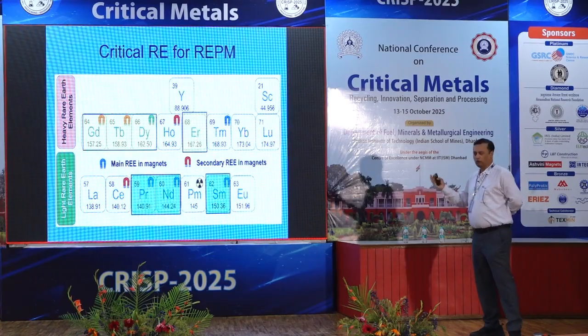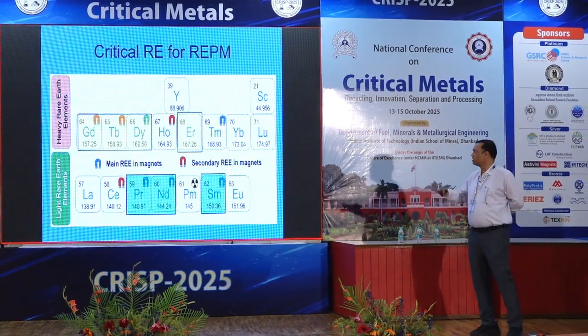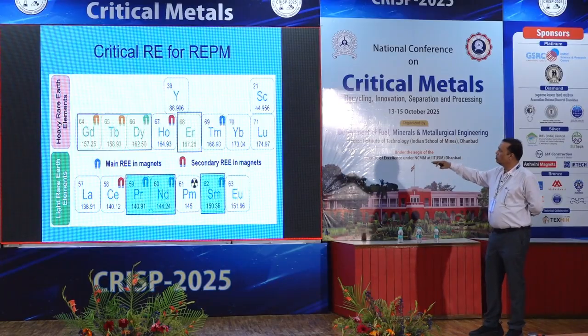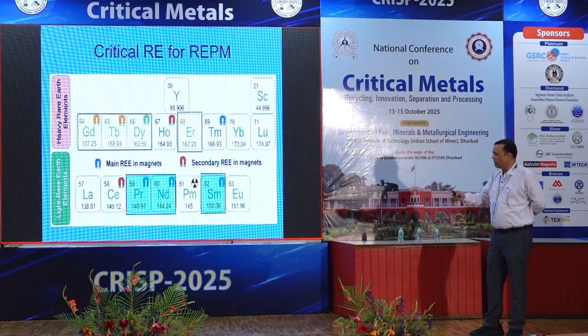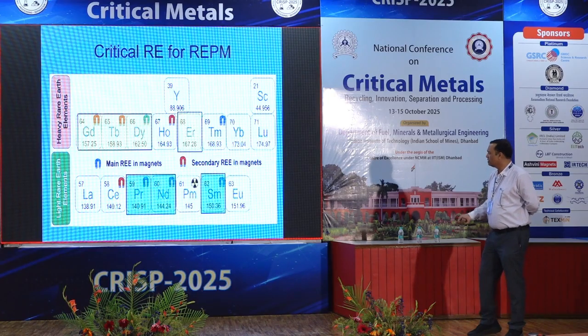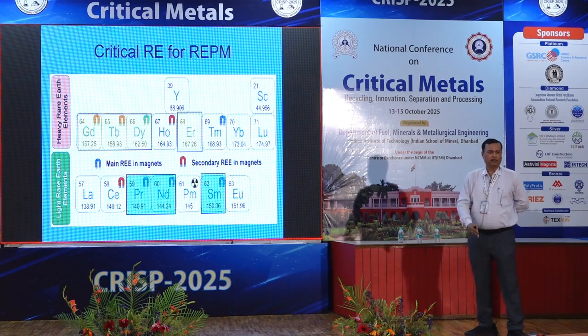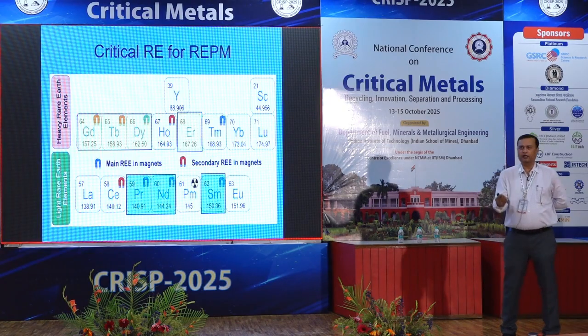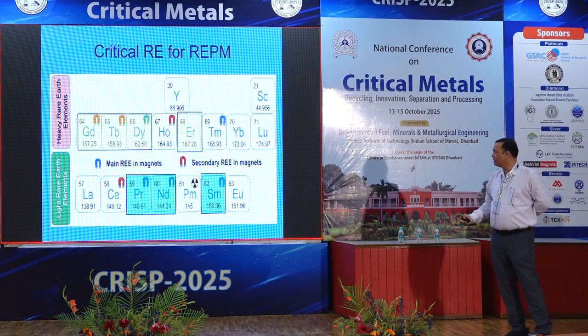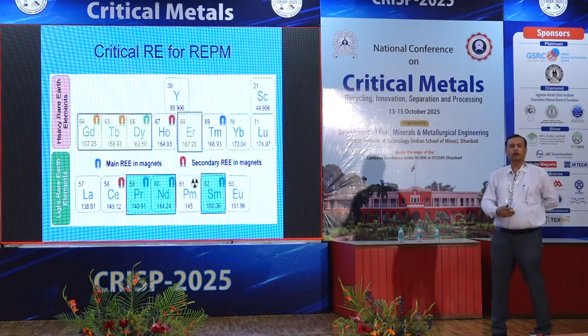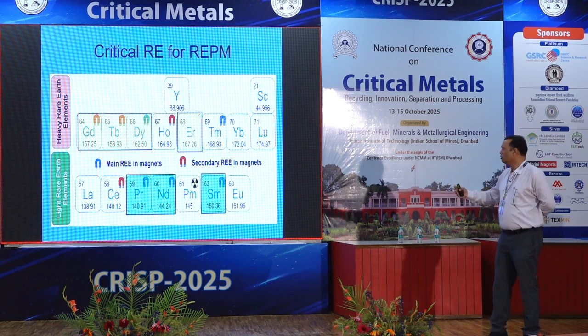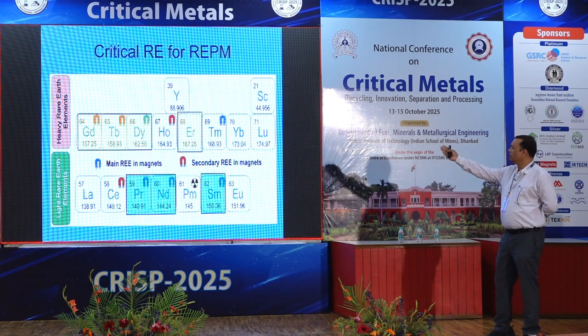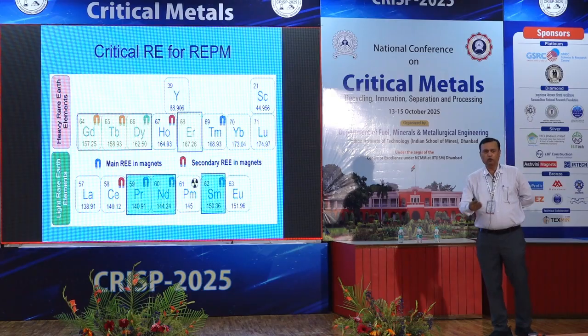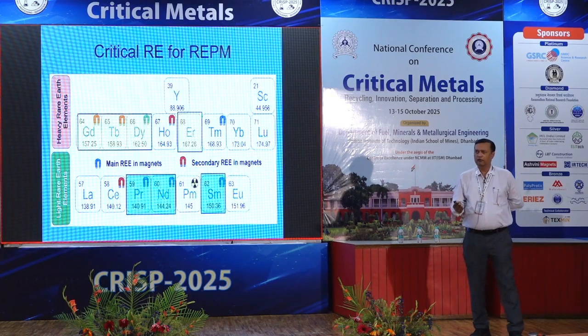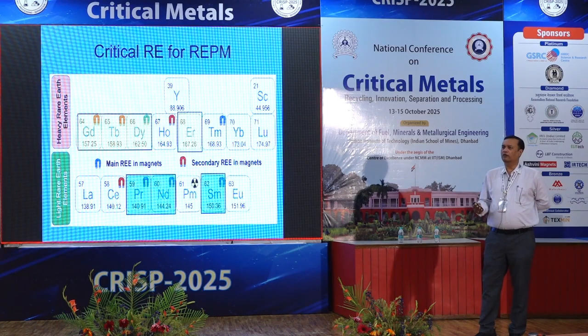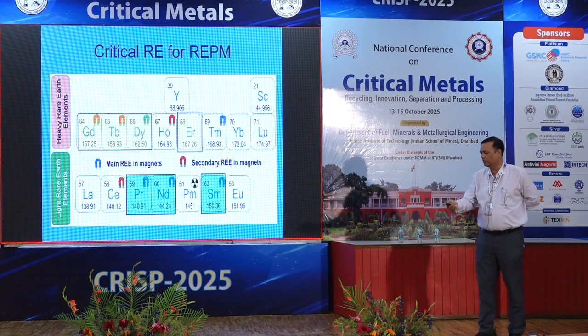If we look at the rare earth elements, we have around 17 elements in total. We can classify them into two: heavy and light rare earth elements. For magnet making, light rare earth elements like samarium, Nd and Pr are required because they couple ferromagnetically with iron or transition elements. Whereas when we want to improve the performance of rare earth permanent magnets, we have to look for heavy rare earth elements like Gd, terbium, dysprosium, erbium. They couple antiferromagnetically with iron and increase the intrinsic coercivity of rare earth permanent magnets, thereby increasing the operating temperature of the magnet.